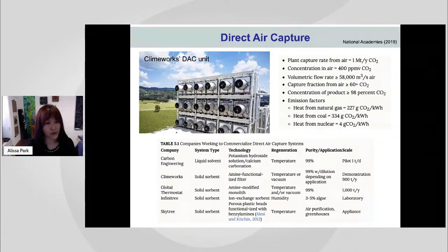The target is also quite different. Because the CO2 concentration is not high, it's only 400 ppm. I think right now it's about 420 ppm in air. Because of that, capturing 95% of this CO2 from air doesn't make sense. It would just take way too much energy. So the target is between 60 to 70% CO2 capture, and a lower number would be easier. But of course, you have to move more air through the system.